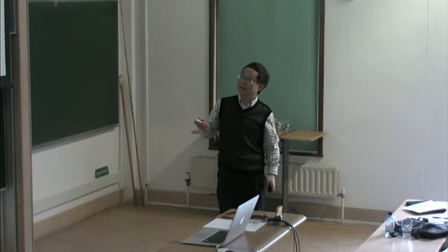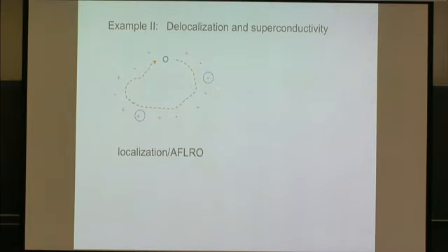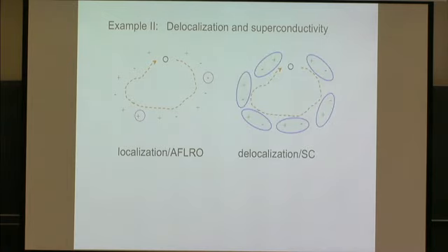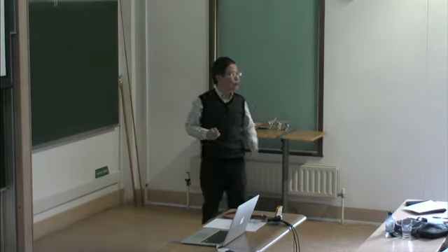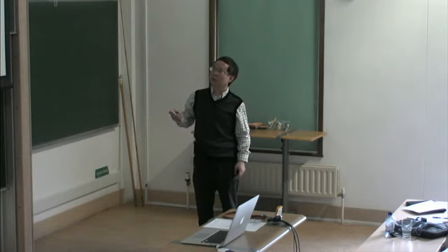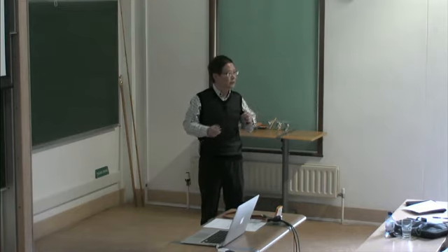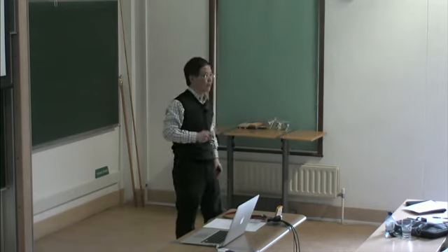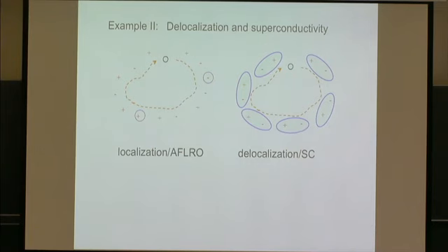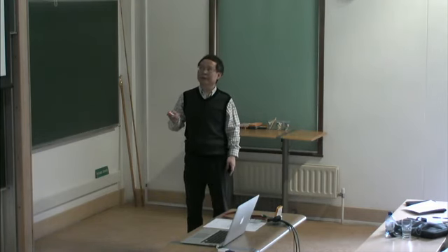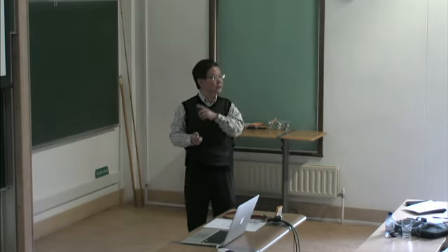So the single hole in a magnetic background picks up this singular sign. It will be localized, and then you can imagine that with a sufficient amount of holes, the localization is not favorable to the kinetic energy. So the holes will try to become delocalized. The way to make them delocalized is to somehow make the spins pair at short range instead of long range, to avoid this long-range phase fluctuation. In this way, you find that the sign could be cancelled out. Presumably, the holes will become coherent and condensed. This is like delocalization, superconductivity happening. So Anderson's original picture of RVB actually emerges here by doping the antiferromagnet into this RVB state.